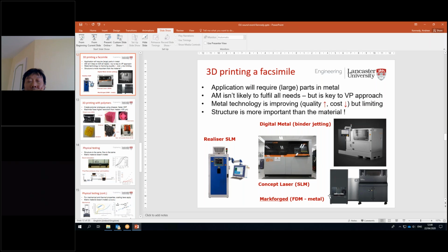So, I think some of the important discussions today, and even relating to what you've said with the fine porosity, is that the different techniques offer different conditions for the cell walls. So, with our SLM process, we will have fairly solid cell walls, the same as we would get from SLA or the PolyJet resins. But the binder jetting is basically like a sort of Z-Corp version of jetting a glue onto a bed of metal powder. So that product needs to be taken out of the bed and then sintered, and you can still have quite a lot of residual porosity in the cell walls. And it may be that once we know more about the system and the modeling, that actually having the residual porosity in the cell walls, like people have shown happens in things like SLS of nylon powders and similar.